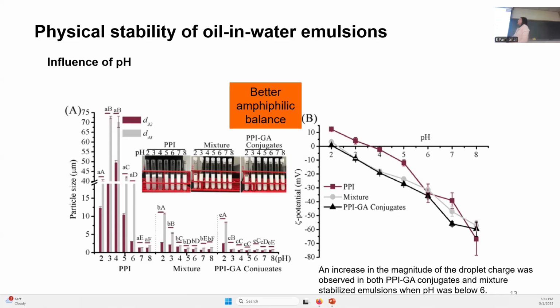That also impacted the stability. So we saw phase separation for the emulsions with PPI at acidic pHs. But for the mixture and the conjugates, we basically don't see any difference in particle size. It's really similar. And the author attributes the improvement in the stability of emulsions compared to PPI to the better amphiphilic balance that was given with the gum arabic added to the system.